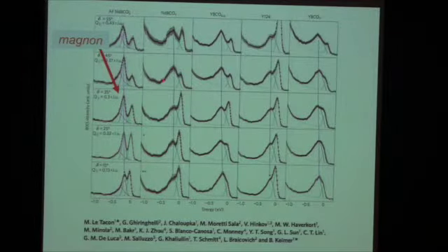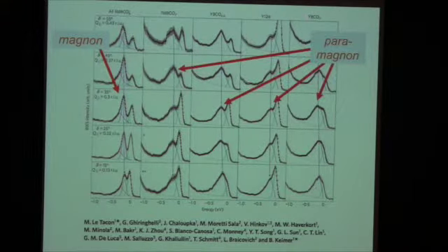Now, these are doped systems. This is weakly doped and more doped. This is, I think, even on the overdoped side. And you see for all these systems, at any doping, the maximum peak remains. It sits there, it becomes broader, but it does not go away.